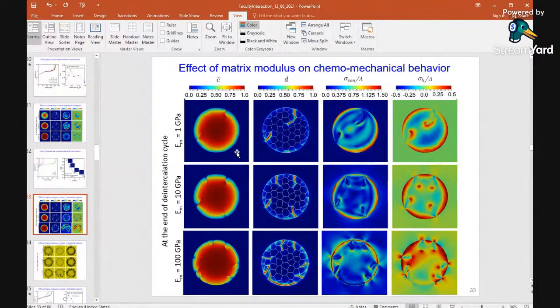What we see in case of this lower Young's modulus is that the crack is generated only within the structure, mostly bulk, and we get interface fracture in both cases. But once we increase the Young's modulus, we see multiple cracks developed. And the most interesting part here is that the particle and the matrix interface is broken. Earlier it was fine; even if there is some crack, those cracks are in the radial direction, so they will not affect the intercalation, deintercalation process much.